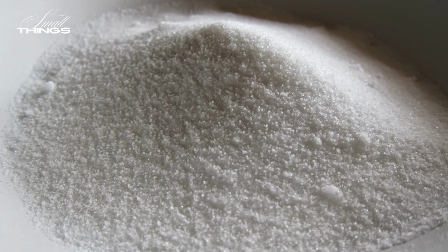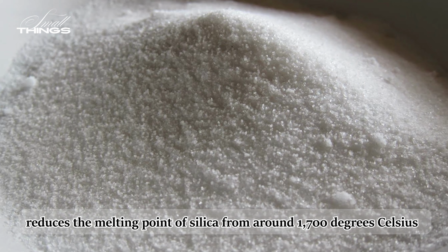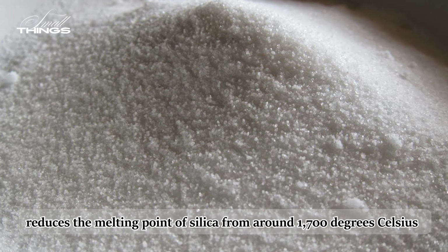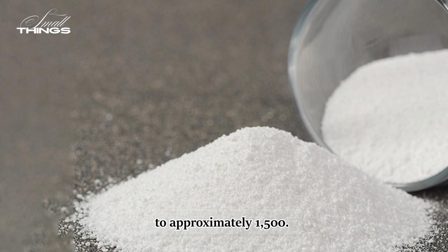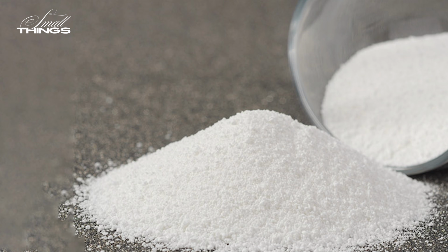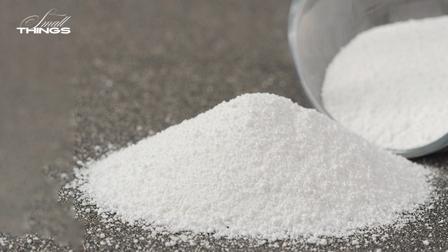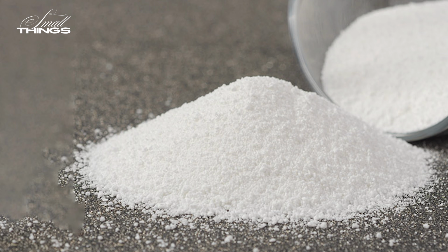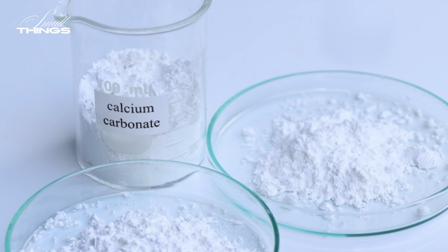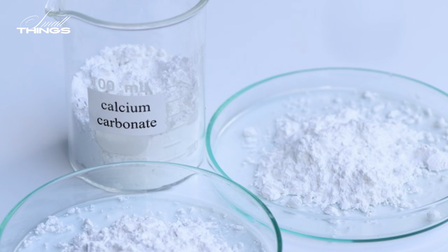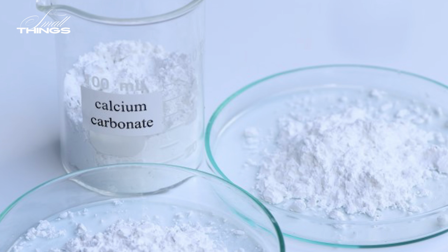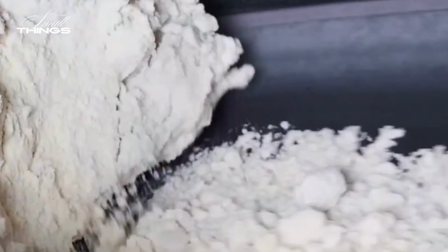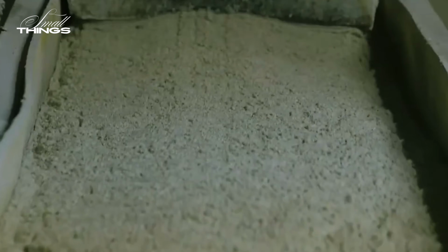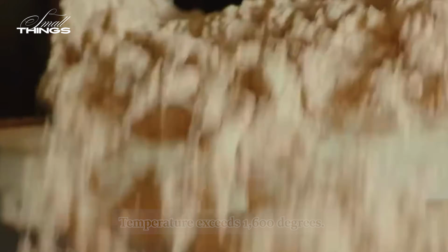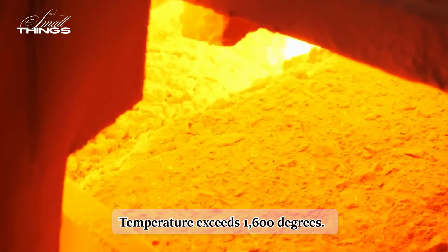Soda ash, sodium carbonate, reduces the melting point of silica from around 1,700 degrees Celsius to approximately 1,500. Without it, the energy required to melt silica at industrial scale would make glass production unviable. Limestone, calcium carbonate, stabilizes the finished glass. Silica melted with soda ash alone is chemically unstable and slowly dissolves when exposed to moisture over time. The limestone holds the structure together. The 3 ingredients are weighed and mixed before entering the furnace. Temperature exceeds 1,600 degrees.